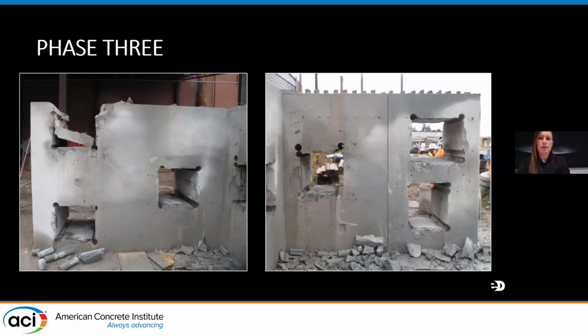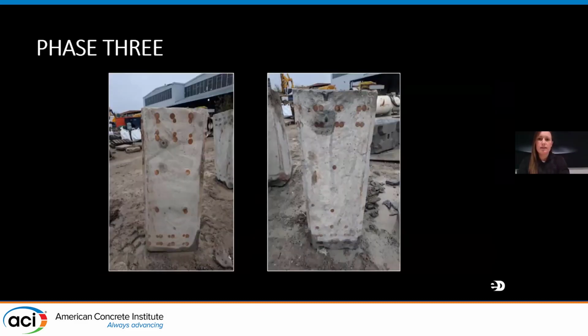And then to further examine the quality of the shotcrete consolidation throughout the full thickness of the mock-up, we ended up extracting these 24 massive large blocks from the wall. It took weeks to just even get through the wall, so we only did it on one of the mock-ups. Each nozzleman was graded on the examination of the four sides of their extracted block and the window left behind in the wall. Beyond the exception that I mentioned earlier at the top of that roof section, there were only occasional small discontinuous voids at the congested areas, but overall the quality of shotcrete consolidation and encapsulation of the reinforcement was excellent.